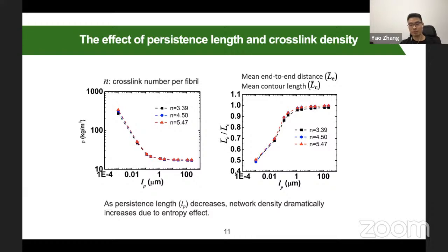What that means is if a network has very stiff fibers, in this case the pore size will increase, and the ratio between the mean end-to-end distance and the mean contour length will increase. That means your mean end-to-end distance increases, and also the pore size increases. If you look at the left figure, it means that in this case the mass density of the network will decrease. So if you have a stiff, thick fiber, the network's pore size will increase, and its density will dramatically decrease.